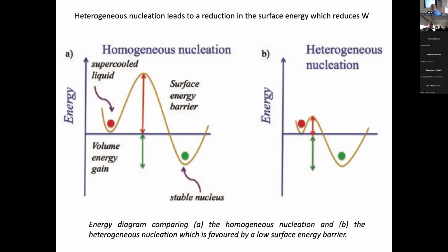First of all, I make a comparison in terms of energy between homogeneous nucleation and heterogeneous nucleation. We need much less energy, and the critical radius has to be smaller, because you already have a pre-existing surface that reduces the surface energy for the nucleus. This is the first point. Therefore, heterogeneous nucleation is much easier to achieve than homogeneous nucleation.